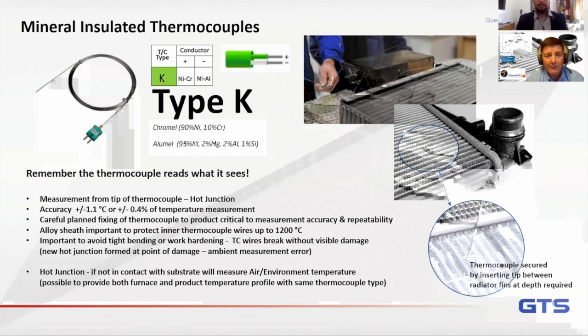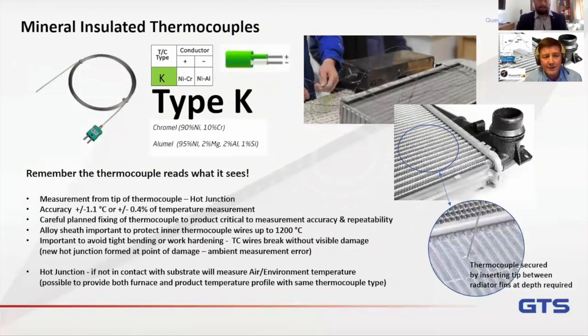Absolutely. The mineral insulated thermocouple, as you can see on this slide, is ideal for the brazing process because the outer sheath, the mineral insulated materials, are fairly robust in the hostile brazing environment. You could use a glass fiber cable in terms of its temperature characteristics, but it isn't going to like the hydrofluoric acid potential damage in the process. So the mineral insulated has to be the go-to thermocouple for this particular application.